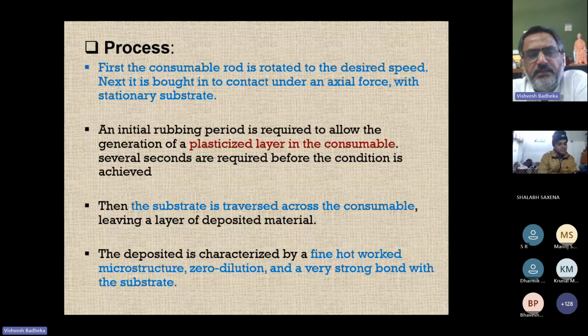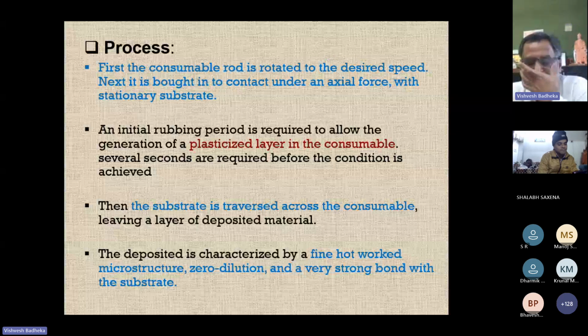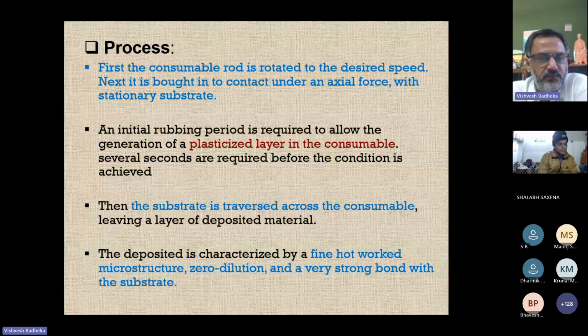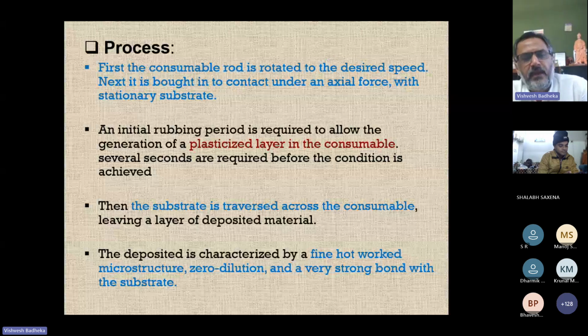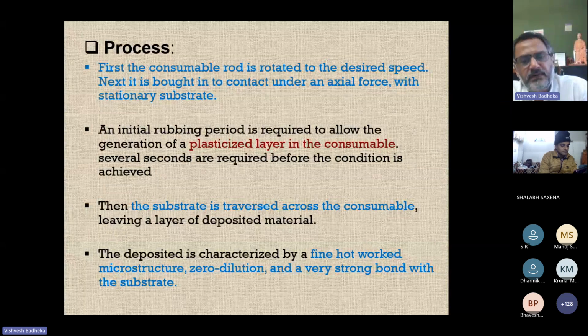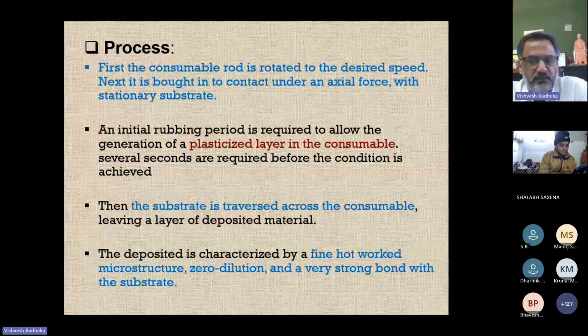So this is the process, as I mentioned. First, there is a consumable rod which will rotate at a certain RPM, and then you bring it into contact with the workpiece under a certain axial force with the stationary substrate. After the initial rubbing period, you can see a plasticized layer forming under the consumable rod, and then the substrate traverse is given. So the consumable rod is getting deposited as a layer, and this deposited layer microstructure is similar to a hot worked microstructure, with zero dilution and a very strong bond with the substrate.